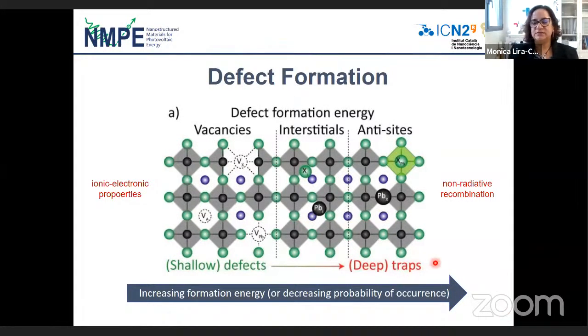In classical semiconductors, shallow defects are negligible—you don't care about them, because you don't have ionic conductivity. So only deep traps are important, and you try to passivate these traps, eliminating this non-radiative recombination.